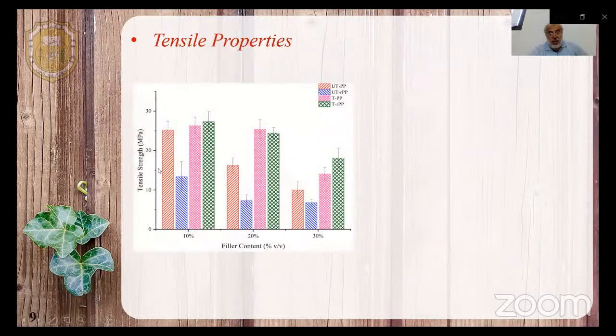For the tensile strength, here we can see the recycled PP based biocomposite has less tensile strength. That makes sense. But when we make the treatment, both will increase, and they are comparable here. And they will decrease as we increase the filler content, due to certain issues, including the distribution of the filler in the matrix, and also the interface, the compatibility between the fiber and the surrounding matrix.